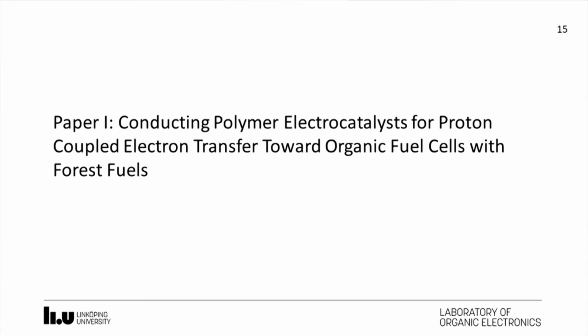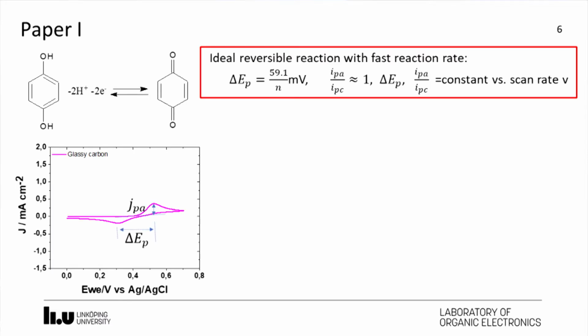First, we studied the electrocatalysis of generic quinone reactions on conducting polymer and for the application in fuel cells. These two proton-coupled electron transfer reactions feature an oxidation and a reduction peak on glassy carbon electrode in the aqueous medium. The peak-to-peak separation delta E and the peak current can give us some information about the reaction rate. For a two-electron reaction, this delta E is about 30 millivolts, and the current ratio should be close to 1, and both of these two parameters will be independent of scan rate.